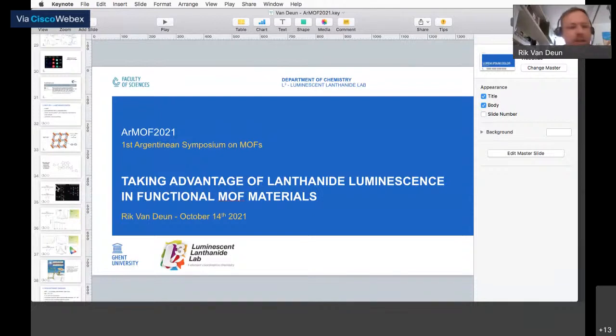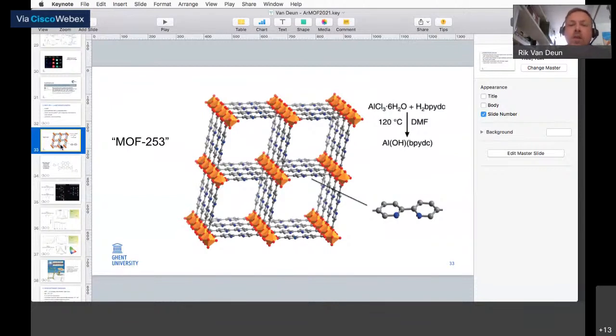Yes, let me see. That's a good question. Of course, when you have a PhD student doing the experiments, it's not always easy to remember how they went. But I think the MOF-253 is a well-established synthesis route. I think you can even buy it. I'm not completely 100% sure. But then the incorporation of the lanthanide complex is typically done, if I remember correctly, by dissolving the complexes in a solvent. For instance, I think they dissolve in chloroform, but I'm not exactly sure. The MOF probably does not dissolve, but you can make a suspension of it, and then reflux these two together for some time. It can take a few hours.